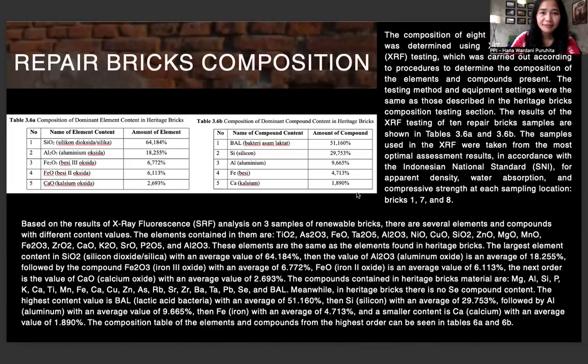Repair brick composition: we can see at table 3.6 the composition of dominant element content and the composition of dominant compound content in table 3.6b. Based on the results of X-ray XRF analysis on 3 samples of renewable bricks, there are several elements and compounds with different content values. The element contents are shown in the table. First, from dominant element content, silicon dioxide, Si, oxygen, and we can see at the top of the table.